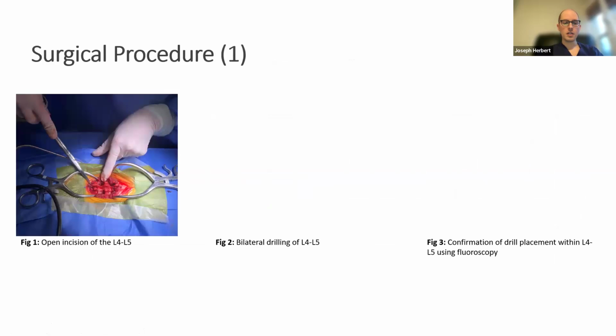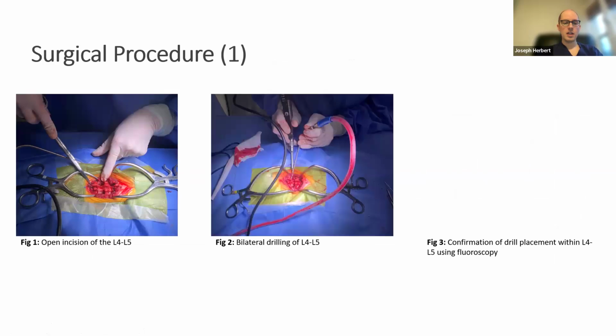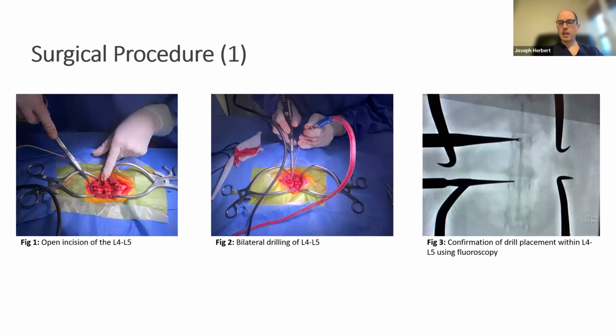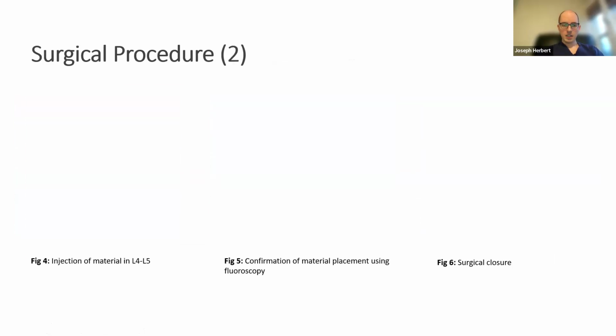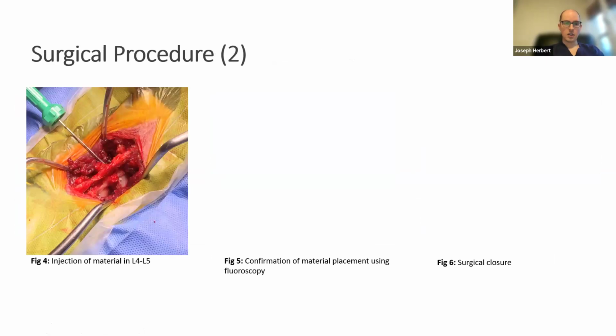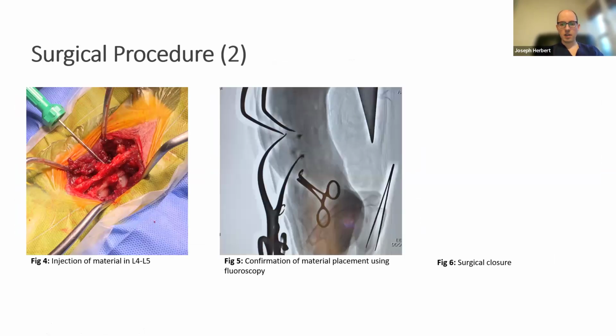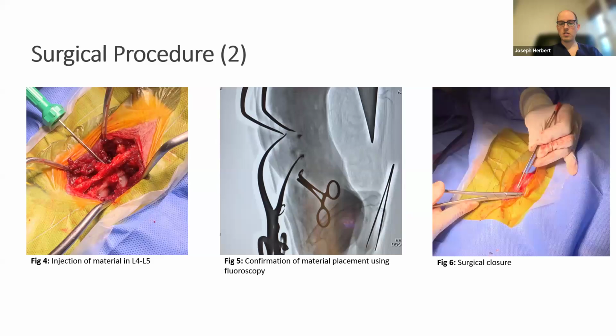So the procedure that they did, and this model of doing a vertebroplasty, they did this open. They drilled L4 and L5, and then they confirmed with X-ray that they were in the right spot. And then they injected this hydrogel. And like I said, the hydrogel before it gelates, when you first mix it up, you've got about 15 minutes or so to inject. They also included a radiopaque dye just to make sure that we were injecting in the correct place, and then they closed up.